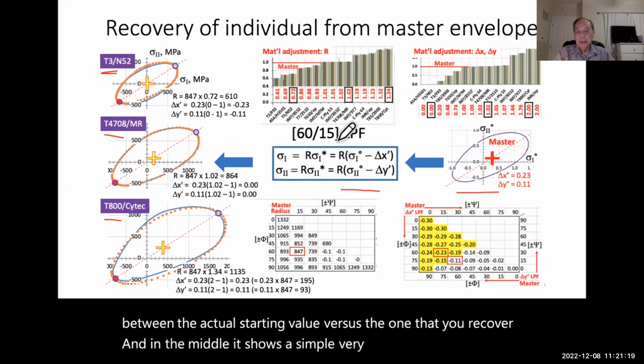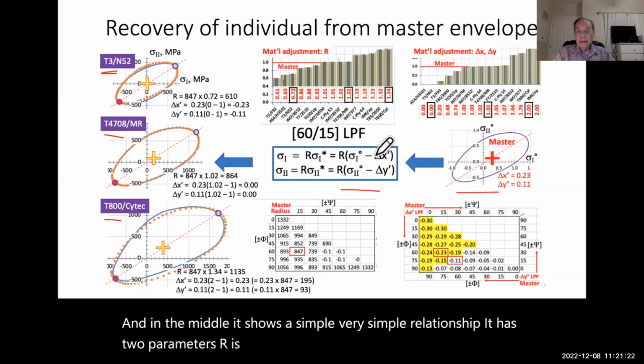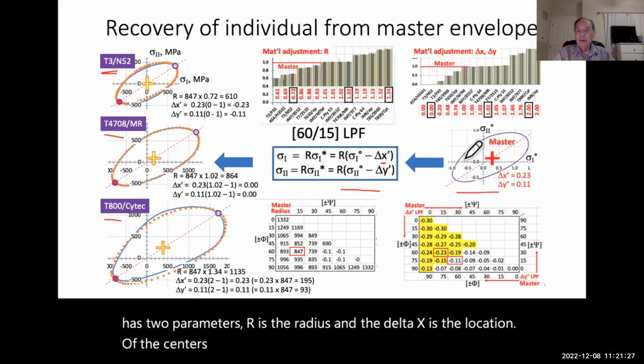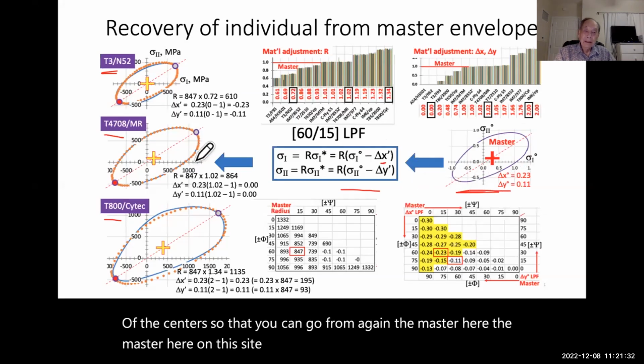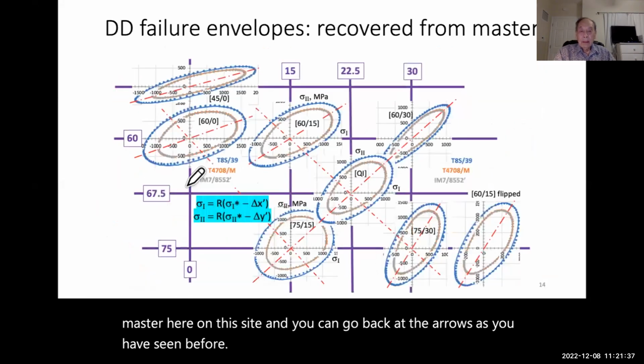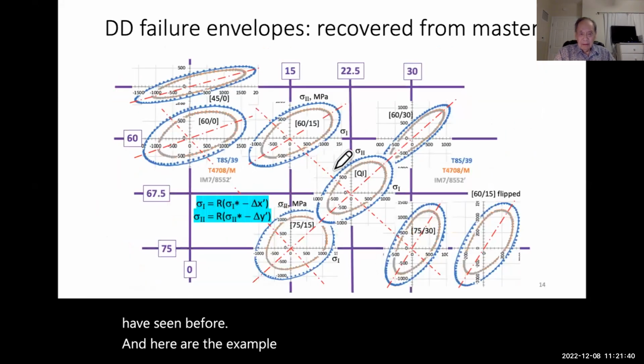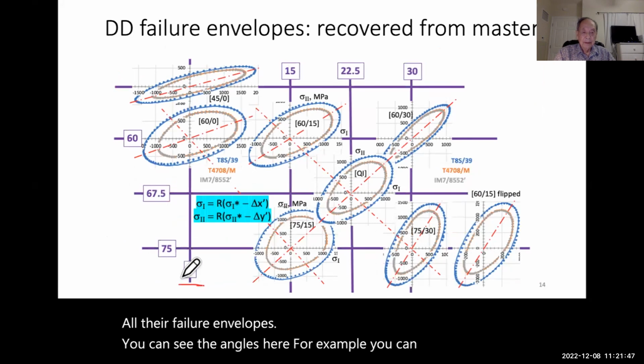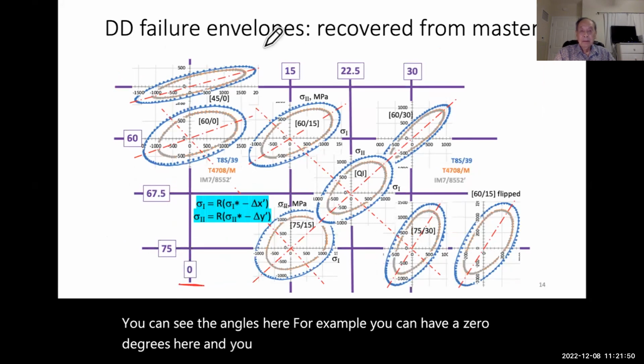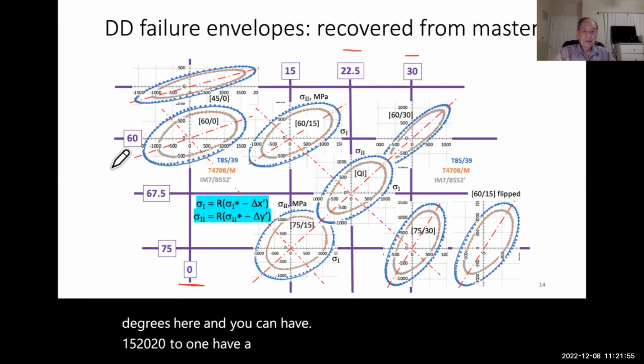In the middle, it shows a very simple relationship. It has two parameters: R is the radius, and delta X is the location of the centers. So you can go from the master on this side, and you can go back with the arrows as you have seen before. And here are the examples of all the failure envelopes. You can see the angles here. For example, you can have 0 degrees here, and you can have 15, 20, 22 and a half, and 30, and you can have 60 and so forth.